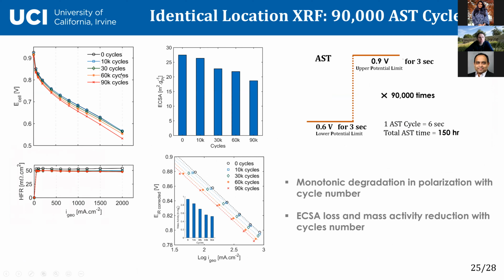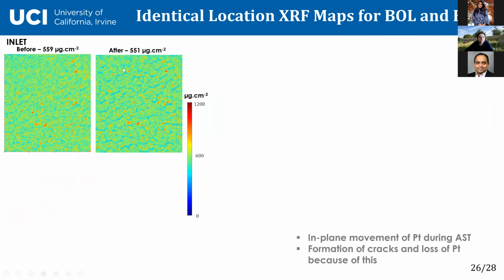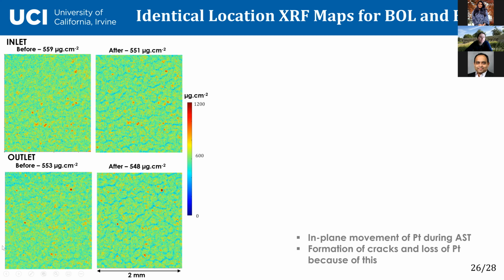Performance, I mean, from beginning of life to end of life, decreased, mass activity reduced, surface area reduced. This is all kind of expected. And these are the micro XRF plots of platinum inside the catalyst layer. And you can see this is loading. Micro XRF captures loading of anode and cathode both. So what we see at the inlet before and after, we see formation of cracks. So all these blue things here are the cracks. At the outlet, we also see a lot of cracks forming in the catalyst layer.